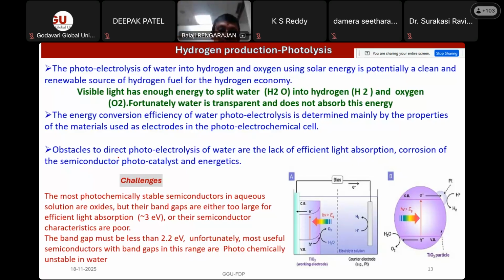These are the two properties essential for any photocatalytic material. There are materials that satisfy one or the other. If you take a material with very good electronic conductivity, it will do the job of converting photons into electrons and electrons into hydrogen very nicely, but that material may not be stable in water. And there are materials which are highly stable in water, but the electrocatalytic activity or electrical conductivity of the material may not be high. Because of this, identifying a proper photocatalytic material that is stable in the aqueous environment and has very good electronic conductivity is the major challenge in the entire photoelectrocatalytic material field.